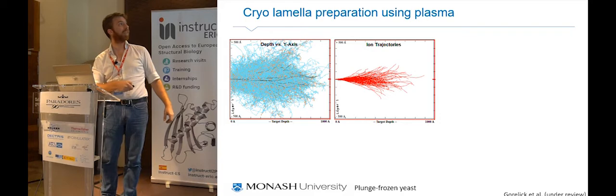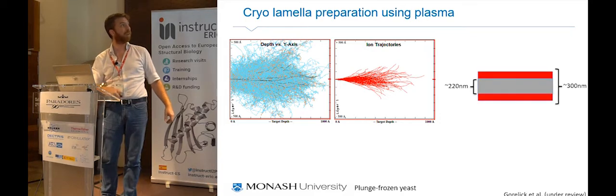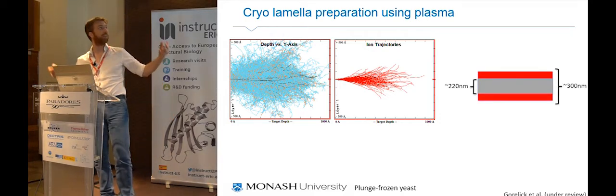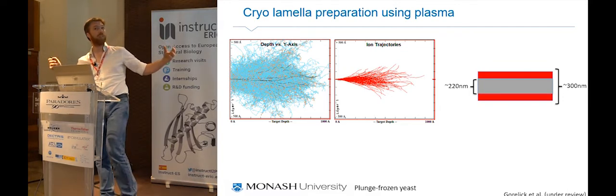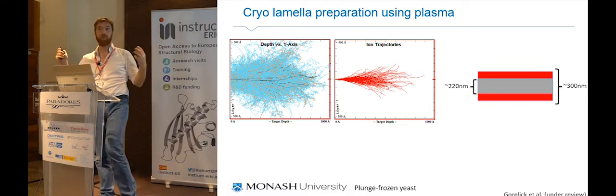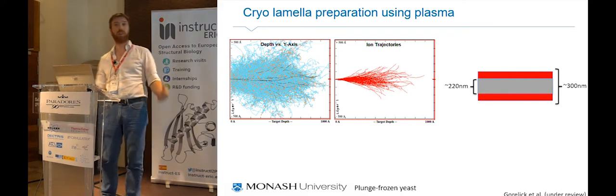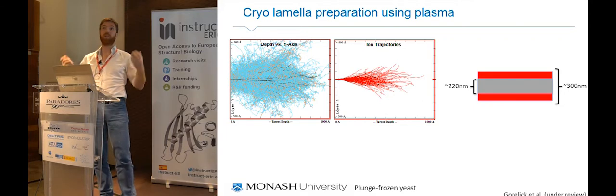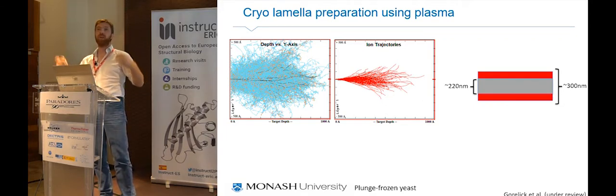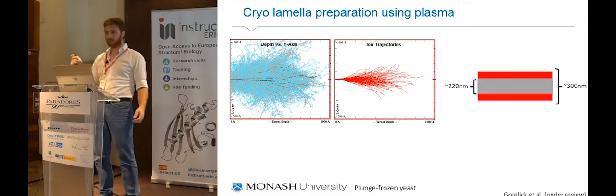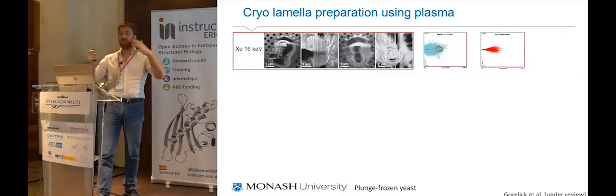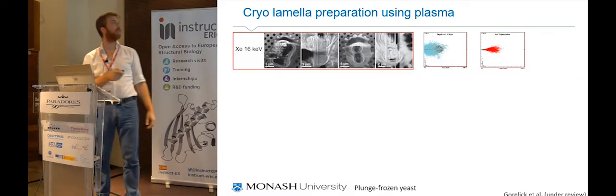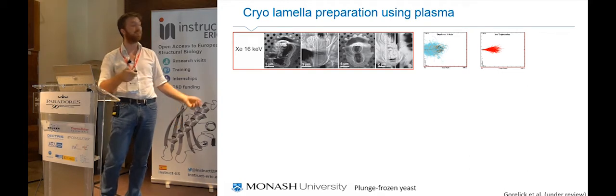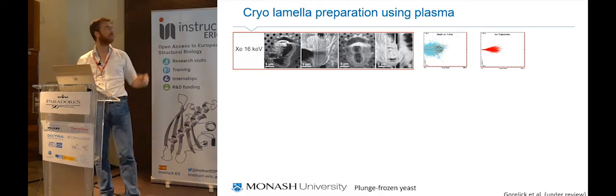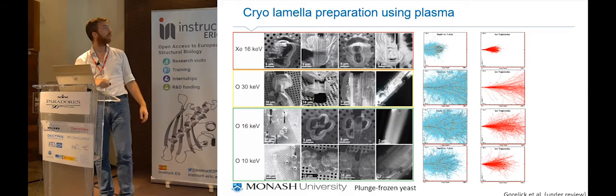So you have a 300 nanometer lamella, and you start shaving both sides, and you're going to have a damaged layer. This damaged layer will depend on which atom you're using, which energy you're using. If you use oxygen at 30 kilovolts, you are actually damaging 140 nanometers per side. The lamella is 300. There's not much left. So we started looking. Xenon is very heavy, shouldn't damage, but it curtains like hell. It's not usable. So that's it. Let's look at oxygen.